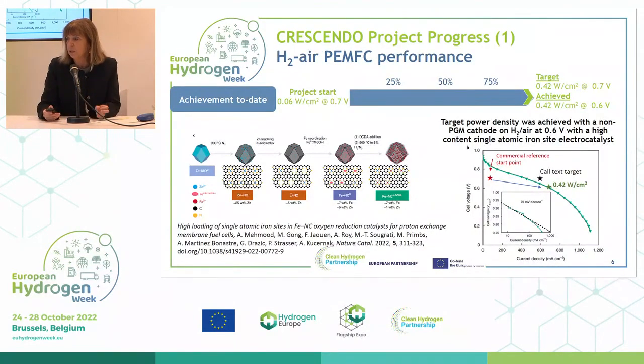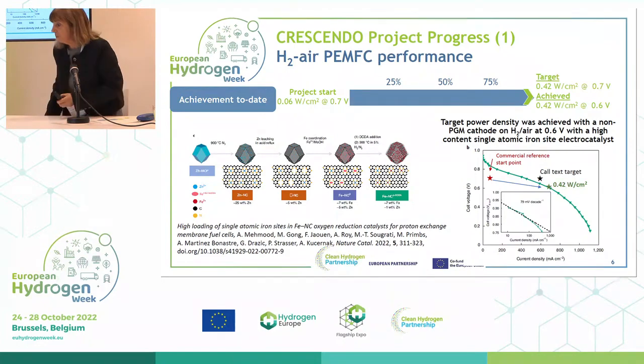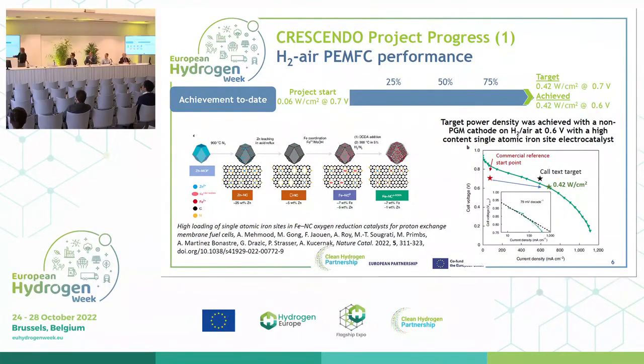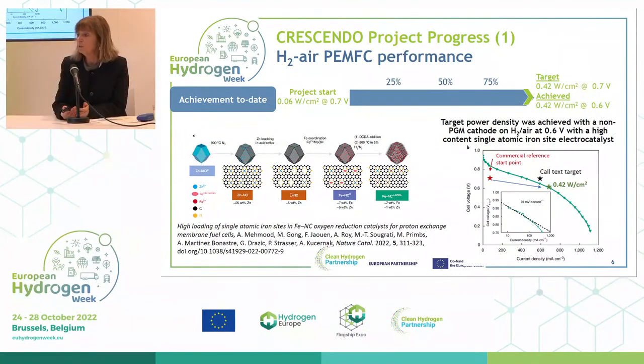So I want to turn quickly then to the progress in terms of performance. And what you can see there at the top in the arrow is that at the project start, that star there was actually the performance that it was possible to get using a commercial non-PGM catalyst on hydrogen air. You can see it's extremely low. Hydrogen air is actually important in this context. You'll still see in a lot of scientific publications perhaps reasonably high power densities, but very often these are on hydrogen oxygen. Hydrogen air performance is quite difficult to get.